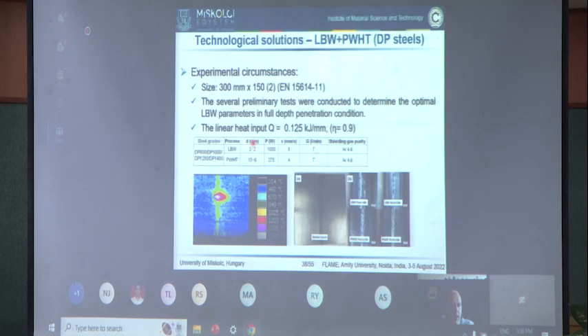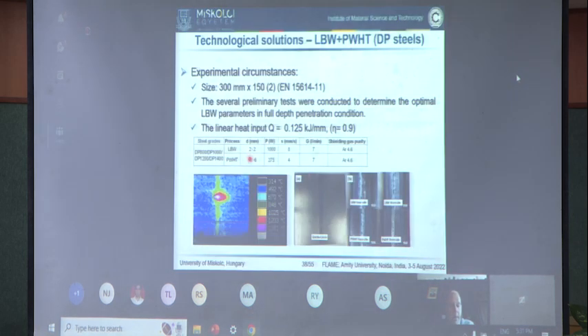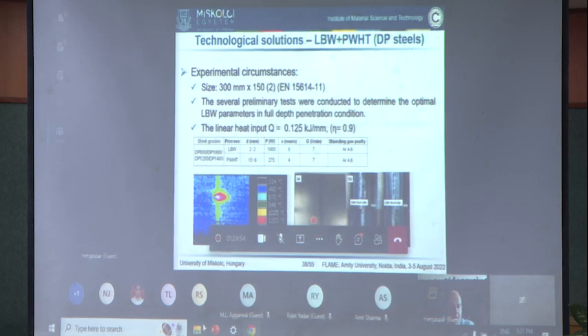You may know that diode lasers are very advantageous because the heated area, the spot size, can be adjusted in a wide range. So for welding, we use a 2 by 2 mm spot size, but for post-weld heat treatment, we use a much larger rectangular shape based on the weld and heat affected zone area.